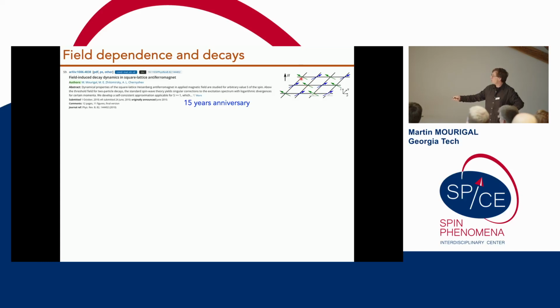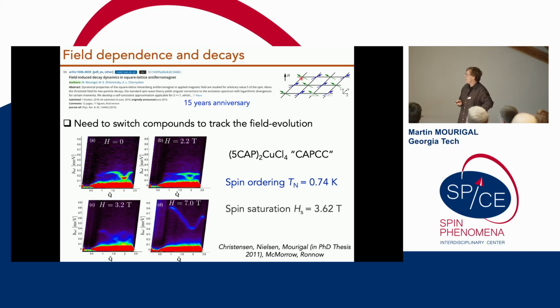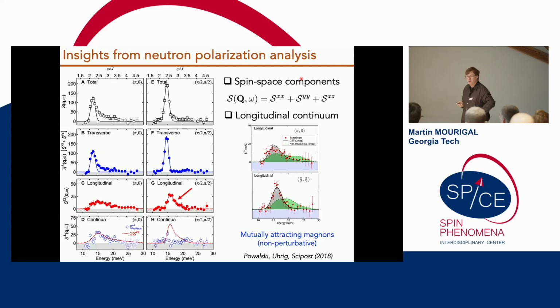And so because you have a non-collinear structure, you're going to have cubic vertices. And so the magnons should be interacting very strongly, with cubic anharmonicities. In fact, a lot of what I've been trying to do since on the square lattice was to track this and to find the effect that above a certain field, roughly 75% of the saturation field, you should have very strong magnon decays.